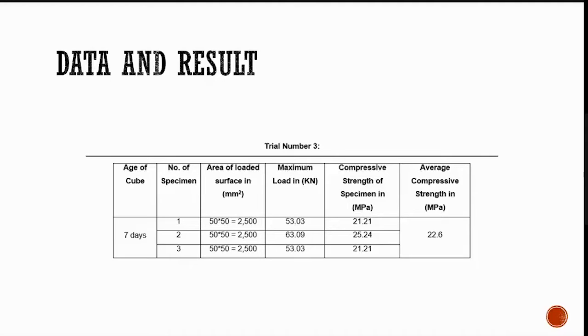In specimen number 2, 50 by 50 equals 2,500. Maximum load is 63.09. Compressive strength of specimen is 25.24. And the last one is specimen number 3. Area of load is 50 by 50 equals 2,500. Maximum load is 53.03. Compressive strength of specimen 21.21. Average of all specimen is 22.6.